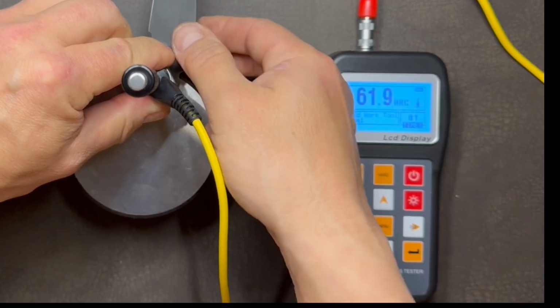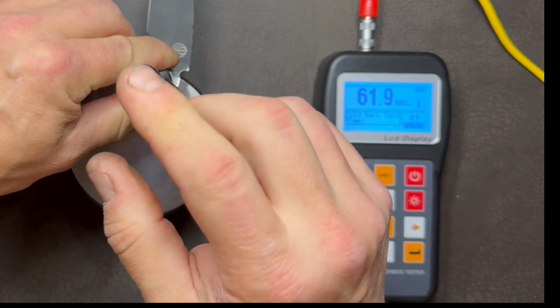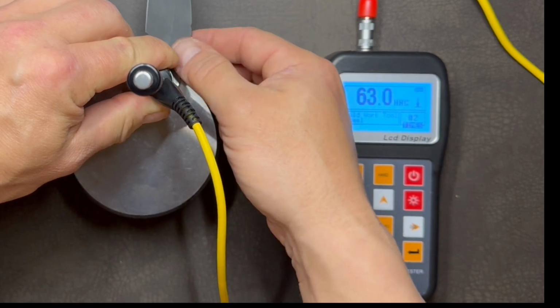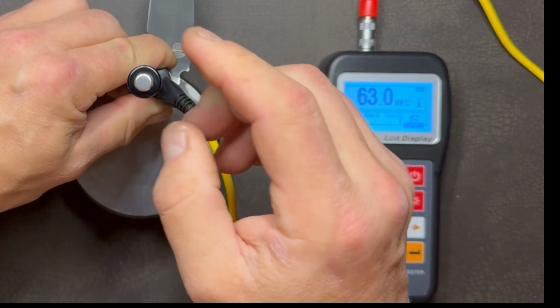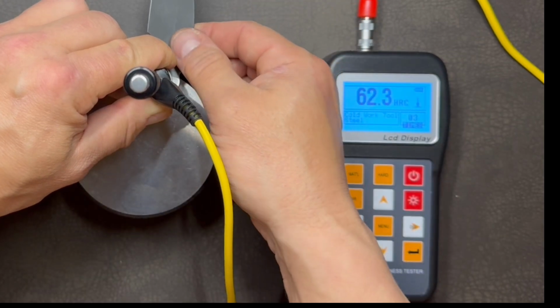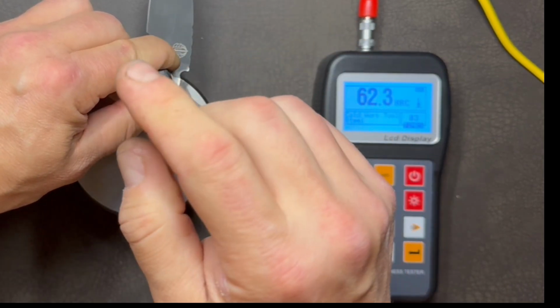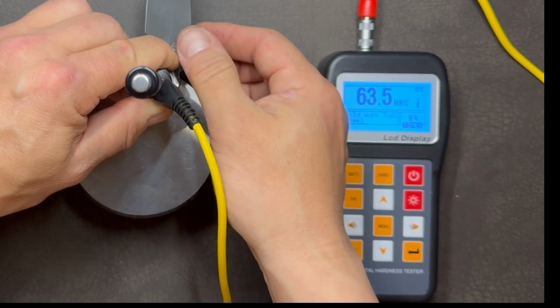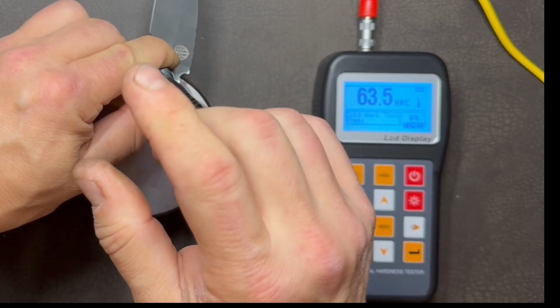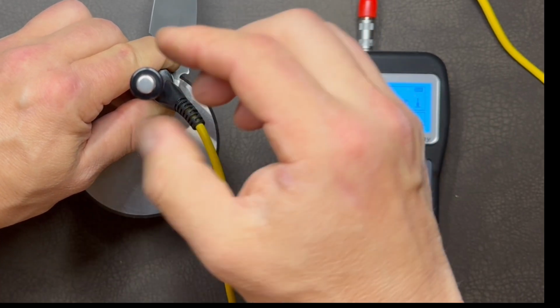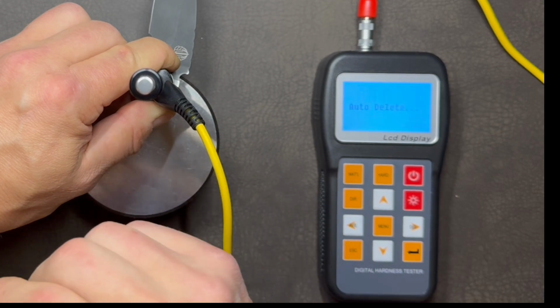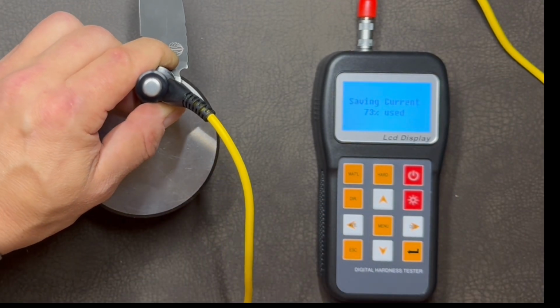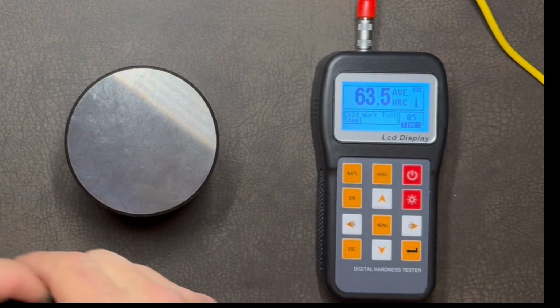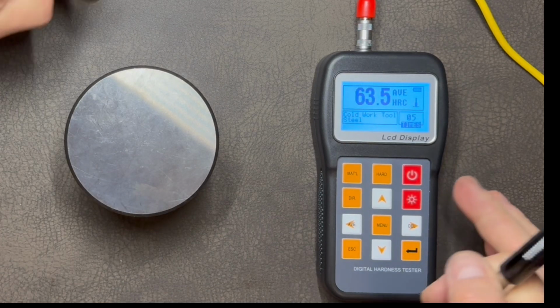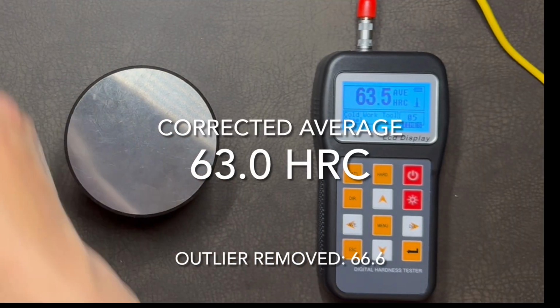One of the biggest channels spreads the word that coating reduces the blade's hardness by 1 or 2 Rockwell points. That depends. If the coating needs to be applied at a temperature that is above the annealing temperature of the blade, let's say 450 versus 350, then indeed it will lower the Rockwell hardness. In the case of less expensive Chinese manufacturers, that may well be the case. At the legitimate manufacturers such as ProTech, an engineer will consider this and adjust the annealing procedure accordingly, so that the additional step of coating does not reduce the hardness beneath the target range, as clearly is the case here.